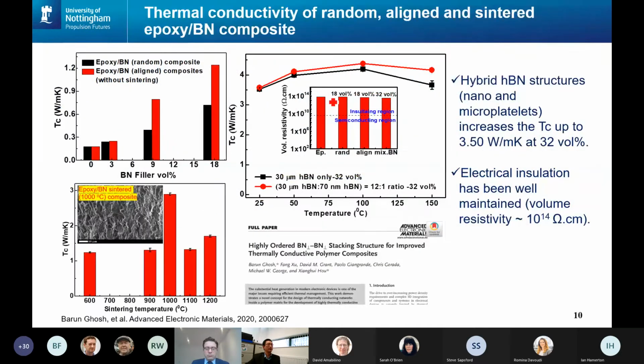So here is the data comparison. The black color is epoxy filled with boron nitride randomly in the composites. Then if we change it with a little alignment, you can see the difference. This is with 18% volume fraction. This is one method. Another method is just sintering this aligned boron nitride skeleton. Especially at a temperature of 1000, you can see it makes a huge difference. It increased from about 1.2 to approximately 3.